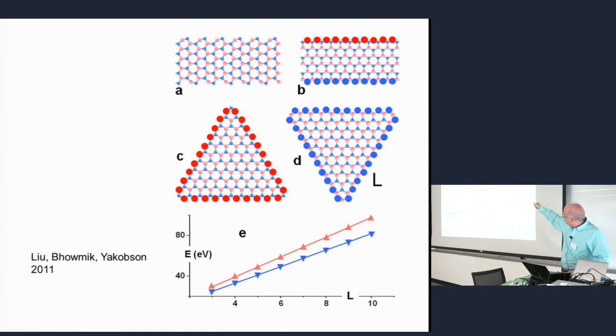This is boron terminated. This is nitrogen terminated. It's more costly because then you have to compute. You have to consider the energy of several triangles, how they scale. But if you do it, then from the slope you can extract a well-defined edge energy, with precision depending on your computations, but at least it's strictly defined energy of this edge and strictly defined energy of this edge. So this was a good step because this allows you to move forward.